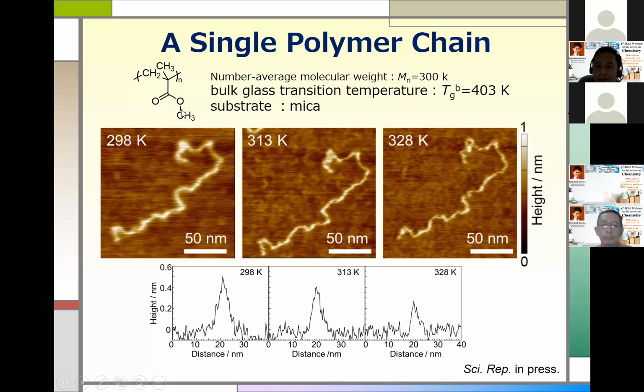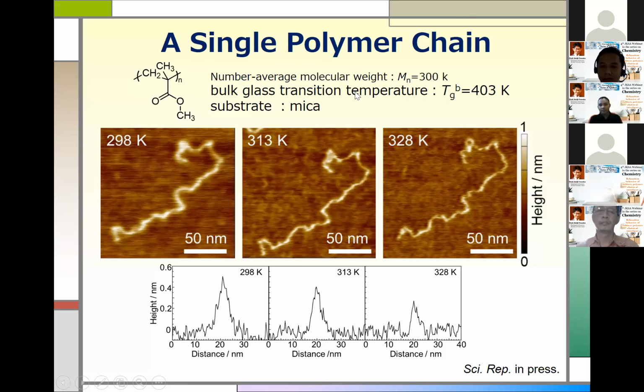The polymer was poly(methyl methacrylate), so-called PMMA. And the molecular weight, this is the number average molecular weight, is about 300,000. And the bulk glass transition temperature of this PMMA was 403K by using differential scanning calorimetry, so-called DSC. And the substrate was mica. We prepared a dilute solution of PMMA in chloroform. And then we spin coated that solution onto this mica, and then the substrate was dried. And then we applied atomic force microscopy. Actually it takes time to look for single chains, but eventually we made it. And you see, this is the polymer chain.